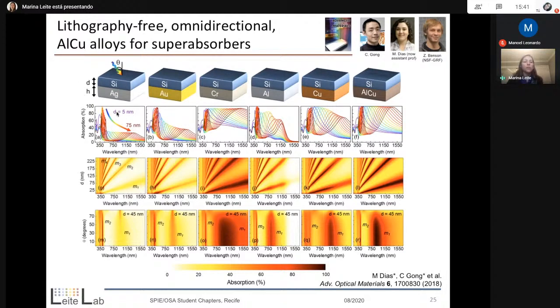Okay, so once we do that, we can select right here in F, this graph I think represents very well, the wavelength range in which you want this very high light absorption. So this is really interesting for a lot of applications. The one thing I want to call your attention to, in the second row, is the thickness of the silicon layer as a function of wavelength. So we can see every single optical mode being excited. And again, for aluminum copper, how those get super, super intense, so the absorption is nearly 100%.